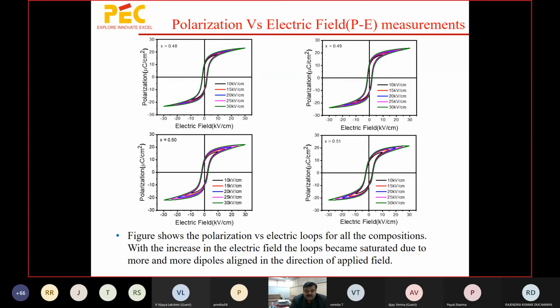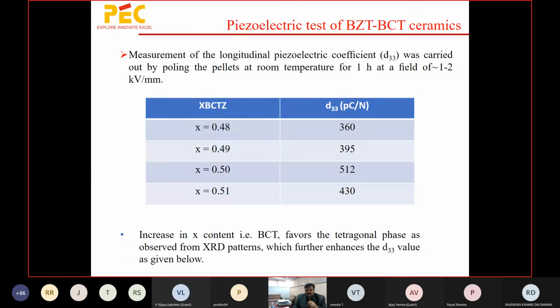And at 30 kilovolt per centimeter, the saturation polarization is very high, nearly 24 microcoulomb per centimeter square, right? So the compositions are very good, meaning we can achieve good ferroelectrics. The main objective is to get the d33, the piezoelectric coefficient. Our aim was to get a value of nearly 400, but the value we achieved for x equal to 0.50 is 512. So that fulfilled our objective.